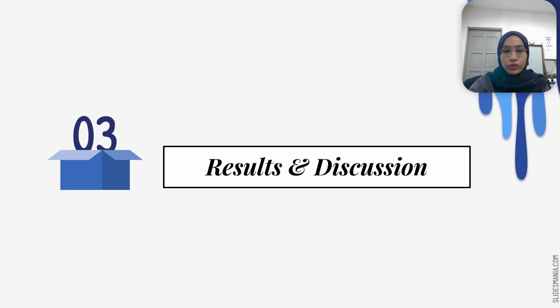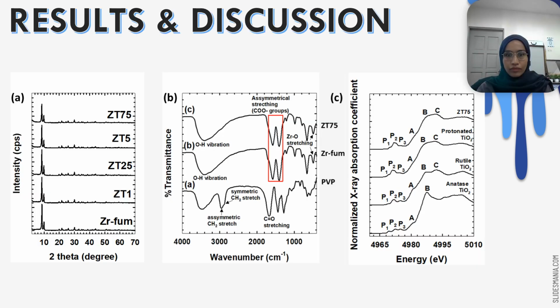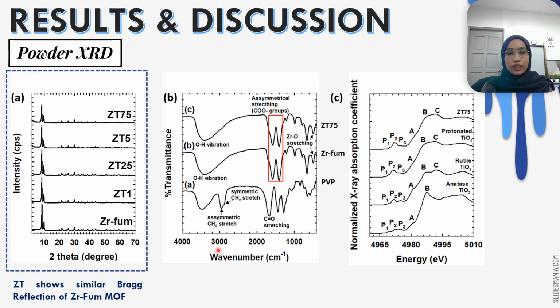Okay, now let's move to the next section, which is results and discussion. I tested all the prepared samples with powder XRD. As you can see from here, ZT means the nanohybrid sample. Z here represents the zirconium fumarate, T is for TiO2 nanosheets, and the different numbers correspond to the different weight percent of the TiO2 nanosheets.